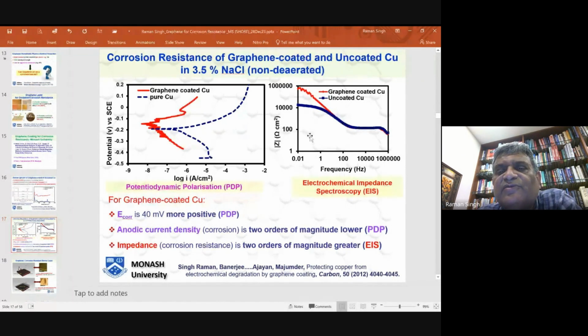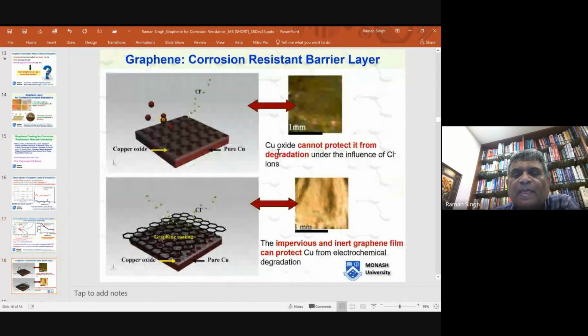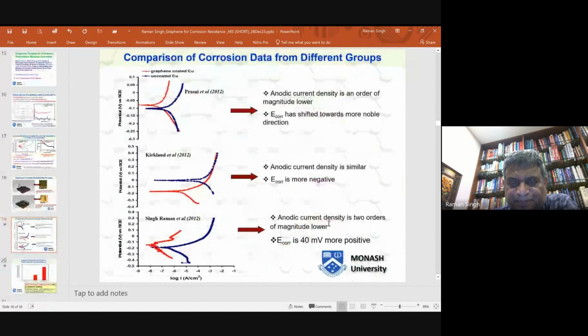And that was confirmed by electrochemical impedance spectroscopy. As I said earlier, the impedance at lowest frequency is a broad measure of corrosion resistance, and you can see 2 orders of magnitude superior corrosion resistance due to graphene coating. And that was confirmed later by post-corrosion microscopy.